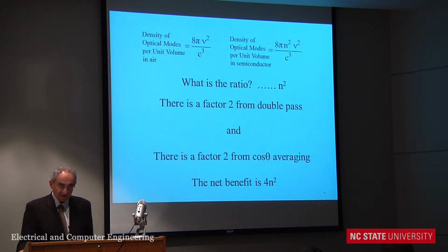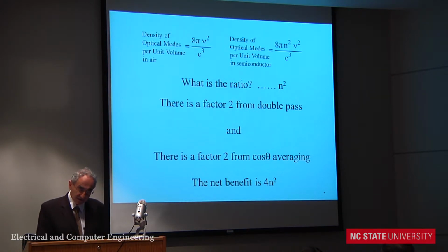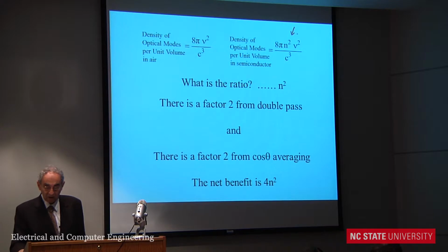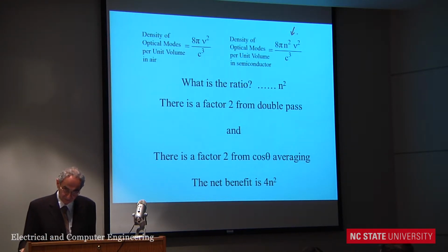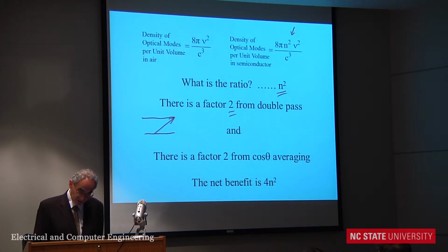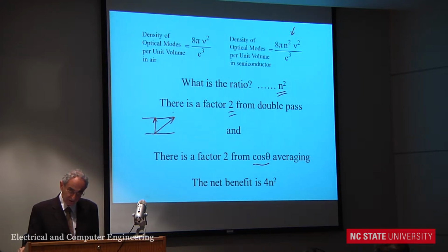Now, people often ask me, yes, this 4n squared factor, but where does it come from? So if you look at the density of optical modes and you do a density of states, there is a refractive index squared that appears in it. So obviously with a high index, there are more wave vectors that are possible. So I pick up a factor of n squared. Then I pick up a factor of 2 from double pass, because if you're just reasonably alert, you'll definitely do double pass to get the most absorption. And then when you're inside the solar cell, you'll be going at an angle, because now all the angles are acceptable, and you have to average over angles. So you have to average over 1 over cosine theta. So compared to going vertically, which is what we used to do, versus going at an angle, you can figure out that 1 over cosine theta averages to 2. So the net benefit then is 2 times 2 times n squared. So that's 4n squared. That is the benefit.